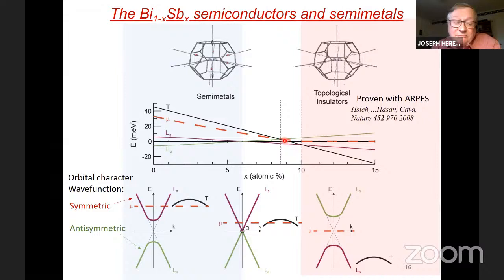But if we increase the concentration a little bit higher, say 9% or 8% or so, the T holes cross, and they go in the gap, and then eventually they come out of the gap on the other side. So here we have a very simple direct gap semiconductor. The gap is narrow, 10 millivolt or so at this concentration, but it can be made very pure. And it is, by the way, a topological insulator with band inversion.